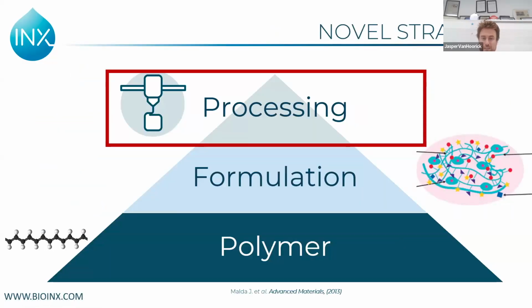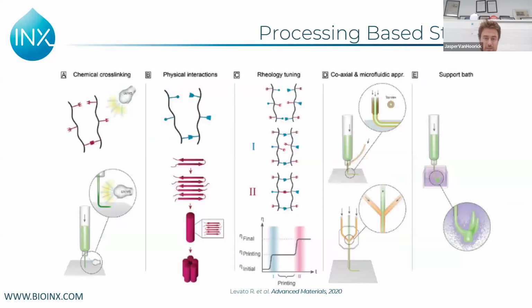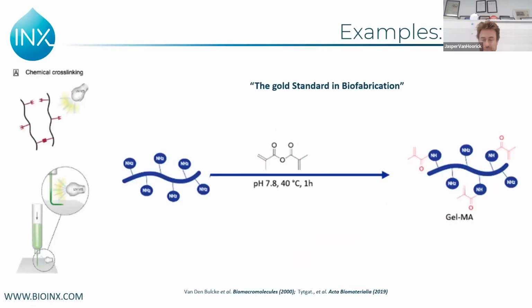On the formulation level, you can also play around on the processing level. There have been many different strategies, as also published in a review by Ricardo Levato from Utrecht again in 2020, where you can see that you can play around with a lot of things. You can do chemical cross-linking, as I already mentioned. You can play with physical interactions to get this shear thinning, physical interaction, rheology tuning. You can have microfluidic or coaxial printing. For example, for alginate, you need a second material with calcium chloride, which you can then deposit together. Or more recently, you can use a support bath.